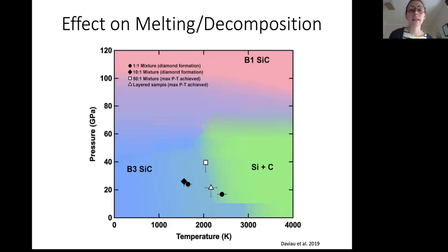But we can look at the effect on melting or decomposition of silicon carbide in these systems. Here I have the pressure temperature conditions where we start seeing carbon diffraction in these experiments overplotted on this tie-dye phase diagram from before. It's largely consistent with that transition that we had seen in the pure silicon carbide experiments. Some of them are a little bit lower, but it's hard to say if there really is an effect of oxygen. It seems that silicon carbide is still breaking up at a similar temperature.